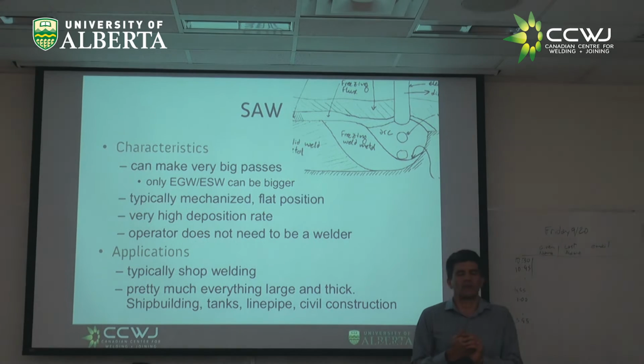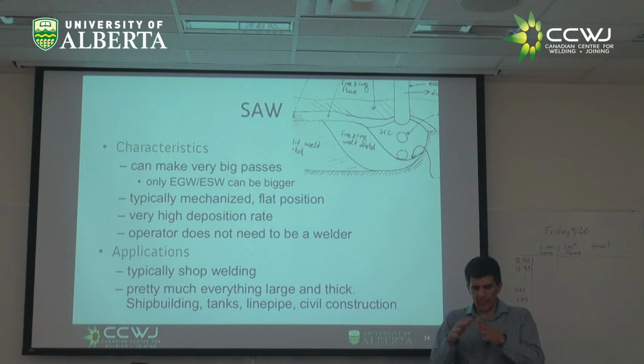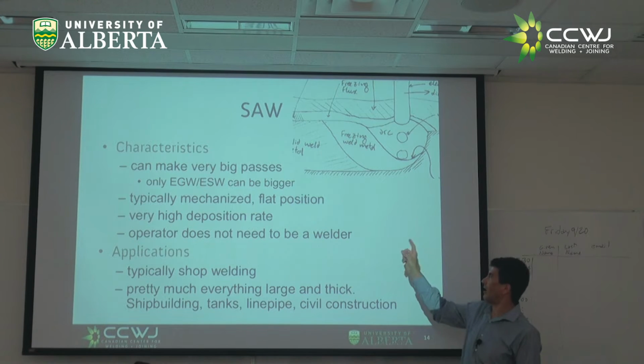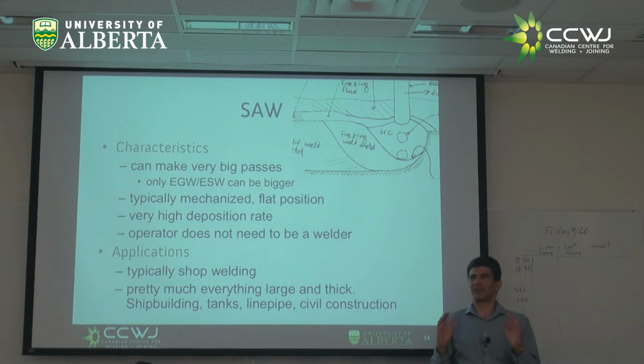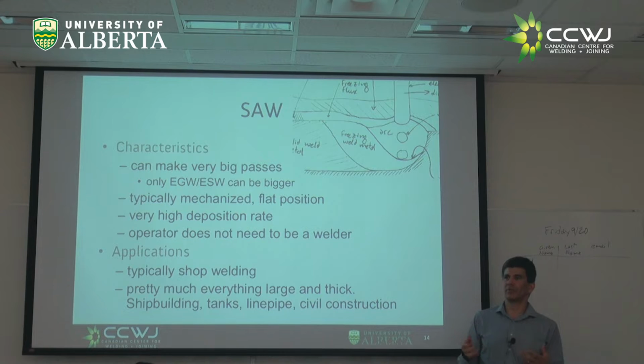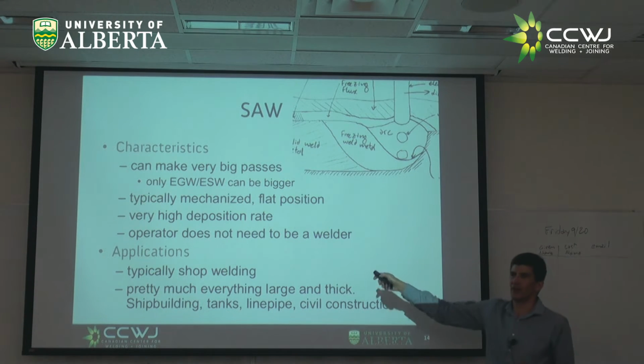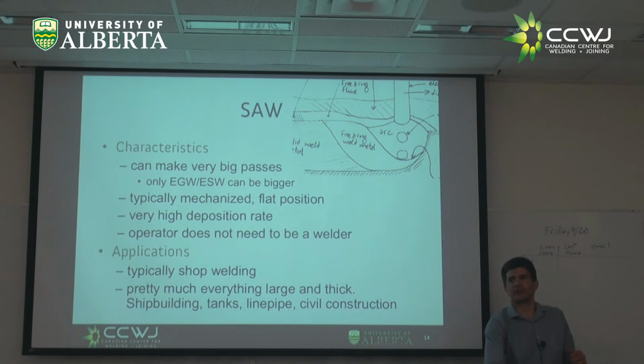So if I have MIG, I have gas shielding, and I protect the tail. If I make a huge weld, it's going to have a huge tail, right? You know this from intuition. We'll give you formulas for that, but typically, big weld, big tail. You cannot shield it with the gas. But with the fluxes, you have all this layer of molten flux, or solid flux, protecting from the atmosphere. For that reason, you can make enormous things.